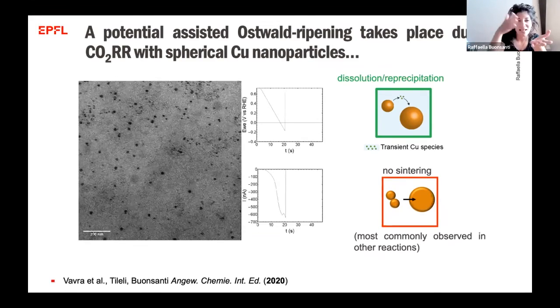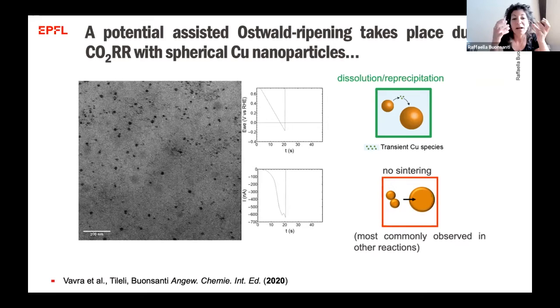And we could study, taking snapshots, how these particles become bigger. What we were able to find is that the particles evolve into bigger particles not via sintering, which is most commonly observed in different reactions, but via a unique dissolution-reprecipitation reaction. And we're now in the process of identifying these transient copper species, which will be interesting to learn more about in order to eventually be able to direct reconstructions while we perform electrochemistry.